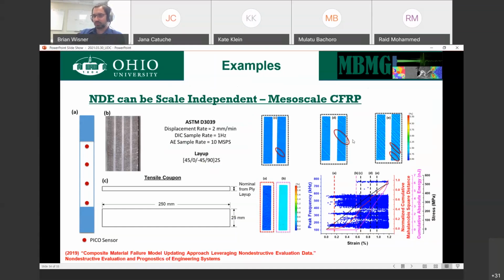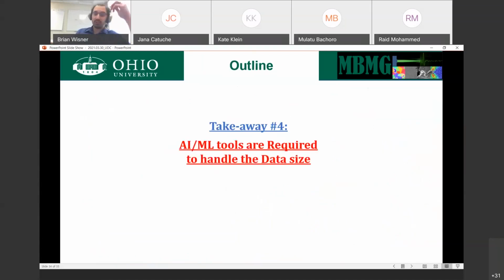It shows me that you have debond from fiber and polymer, but you have no idea what's happening on any of the other layers. And so with acoustic emission, we could start to do this and look at the fact that we have activation of different mechanisms at different times. Now we can start to piece together that this material fails by matrix cracking. Then you have the debond on the fibers on the surface. And then eventually, much later, you have fibers themselves starting to fail. Very helpful. Now, that's nice, but that's a lot of data and very hard to figure that out. And it's a case-by-case situation.